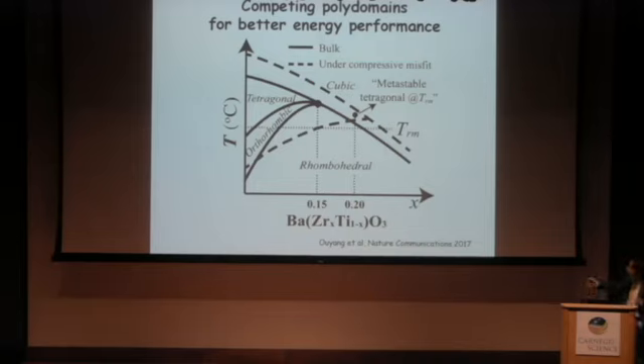You drag the stable phase from tetragonal to orthorhombic until you go to rhombohedral. Until you hit 25% or higher, you get a relaxor, and I don't want to go to that side. So I picked something at 20%. We know it's rhombohedral in the bulk. But at the same time, if you grow a film of this composition on a substrate, the symmetrical in-plane compressive stress will stabilize the tetragonal phase, as we all know from the classic case of bismuth ferrite. So if the bulk stable phase is rhombohedral, but we grow it on a cubic substrate, I can stabilize my tetragonal phase.